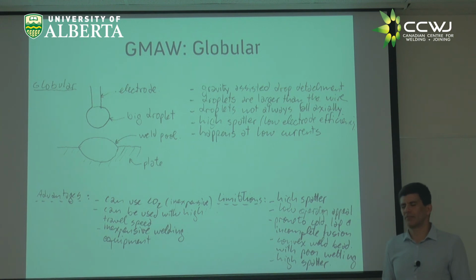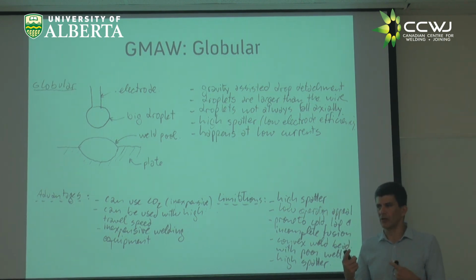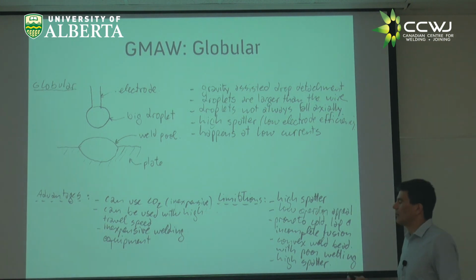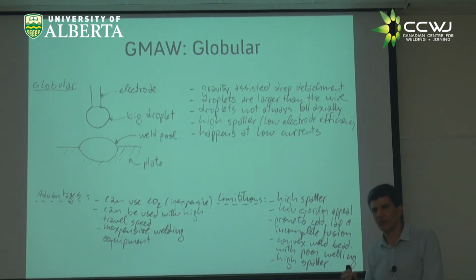So now it's a funny trade-off. I want to use a cheap gas such as CO2, I'm going to end up with a pretty crappy metal transfer mechanism. Sometimes it's okay, sometimes it's not okay. But now you start thinking, oh, can I deal with lots of spatter? Maybe you're making a weld that is so big that you don't care, right? Sometimes it matters. So high amounts of CO2, and by high amounts I mean above 25% CO2, will give you globular transfer.